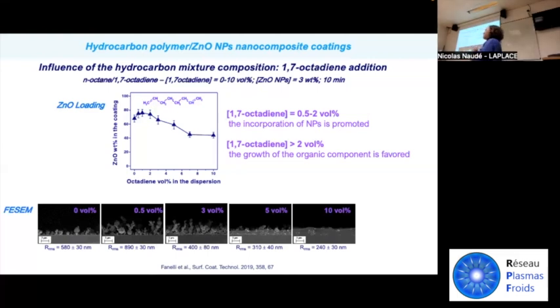Then you need to think about the thickness, the gas injection, to really have a uniform coating, and then also the aerosol. It would be better to use plasma enhanced chemical vapor deposition rather than nanoparticles, because you can have some obstructions. So the limitation, for the moment, is that we did not really use pores less than 300, 200 microns. And we always use a fully interconnected porosity, because if there is not a fully interconnected porosity, you can have several non-uniformities.